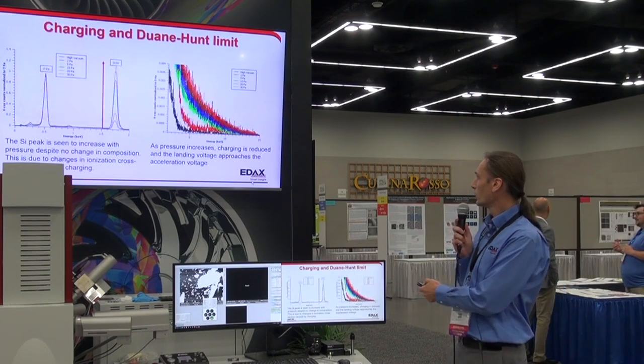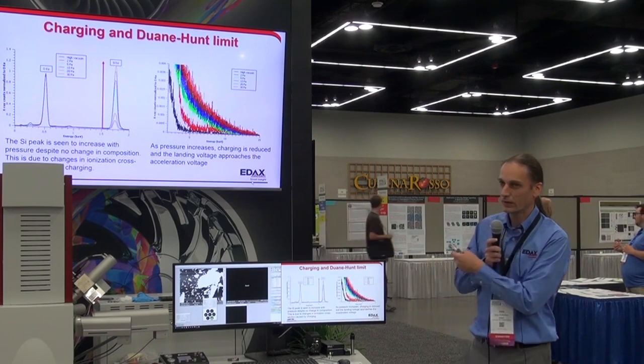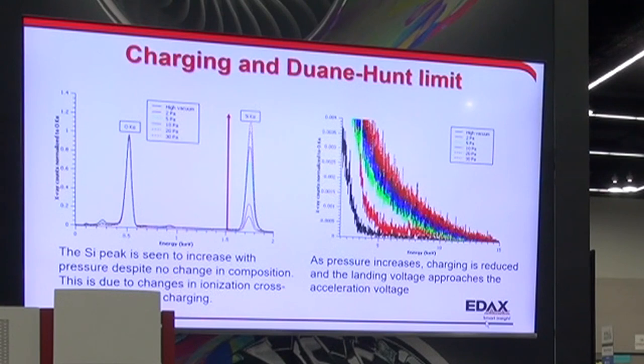Normally we plot spectra so you don't see the tail. You don't always have charging. But if you have samples that you think may be charging, it's always a good idea to look at this tail off the background — see where it trends off — to see if you have charging on your sample. That piece of information is hidden in the background tail, and it's already there, so make use of it.